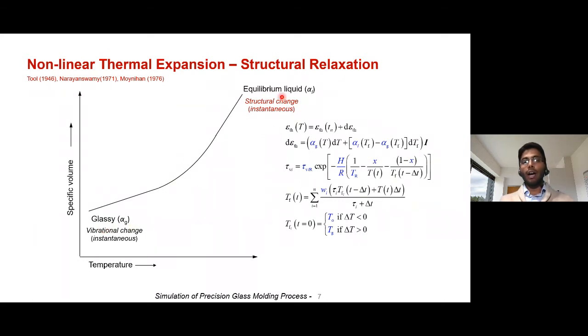Whereas at higher temperatures, the vibrational change is not so important. The structural change mechanism comes into play. When I say structural change, it means that the molecules of the glass, the bonds, break and reform again. That happens instantaneously when I'm cooling at a very high temperature, let's say from 1500 degrees centigrade to 1400 degrees centigrade. In that range, there is a structural change happening very instantaneously.